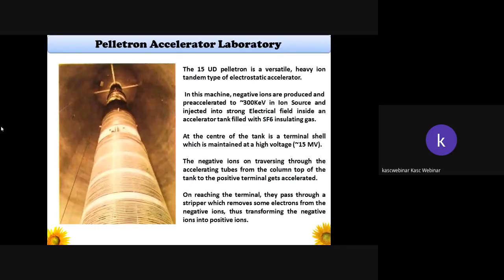This is the inside view of the Pelletron accelerator 15 UD, and it's a versatile one. It's a heavy ion tandem type electrostatic accelerator. In this machine, negative ions are initially produced and pre-accelerated to 300 kiloelectron volts, a very minimal amount of energy, in an ion source, and are injected into a strong electric field inside an accelerator tank filled with SF6 insulating gas. At the center of the tank is the terminal shell, which is maintained at a very high voltage, 15 megavolts, and these negative ions traversing through the accelerating tubes from the top of the tank to the positive terminal get accelerated. On reaching the terminal, they pass through the stripper, which removes some electrons from the negative ions, thus transforming the negative ions into positive ions.